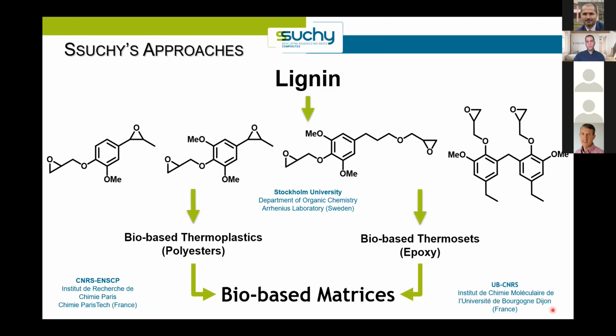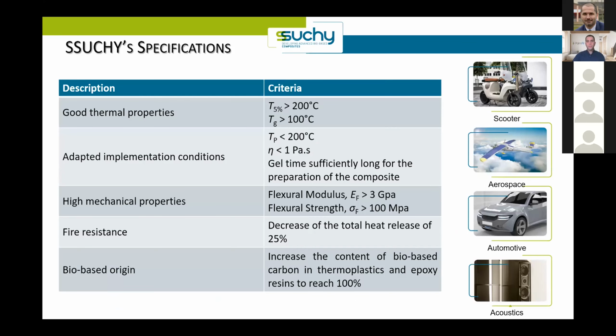So the goal of our work in that case was to find new synthetic approaches to fully bio-based polymer materials in order to replace petroleum-based polymers. And this work was carried out in Dijon and in Paris, and was in close collaboration with Stockholm University. And we were interested in two different routes involving the development of new thermoplastics, but also in the development of thermoset epoxies. In the SSUCHY project, we had several specifications to meet. First of all, we wanted to obtain good thermomechanical properties with, for example, a high transition temperature above 100 degrees. Also, the improvement of the flame retardant properties of the synthesized material was particularly targeted. And of course, it was important to increase the content of bio-based carbon in thermoplastics and also in epoxy resins.